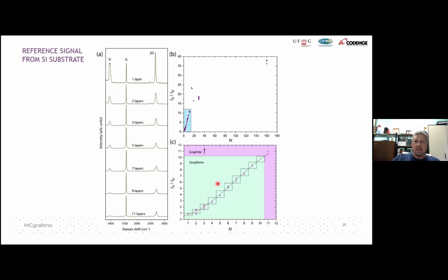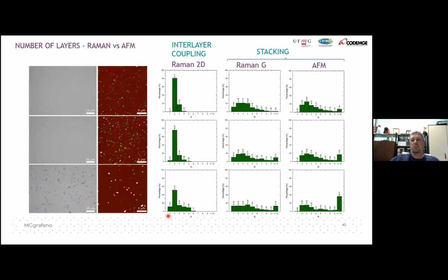And then we make some standard measurements again, and then we measure the G-band intensity, and we can reproduce, okay, much better the AFM measurements. So in this case, the Raman communicates nicely with the AFM, okay? And what we call this is like the data from the 2D band is not waste, okay? It tells you how much of your planes are uncoupled, okay?